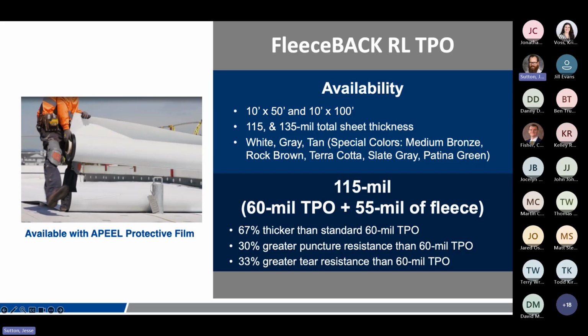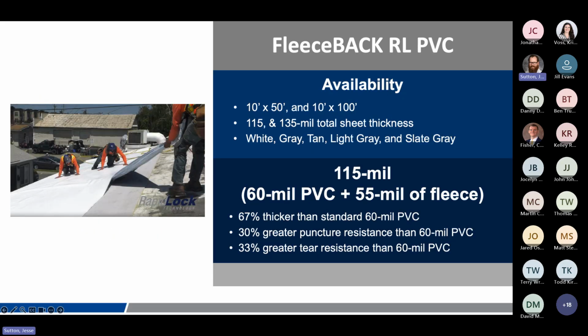Down below there, again, similar performance. We have the increased thickness due to the fleece, 30% greater puncture resistance than a bareback sheet, and 33% greater tear resistance, again, with adding that exterior reinforcement. Just to move on to the PVC offering, again, you can see the roll sizes there on your screen, 115 and 135. A little bit different. We have stocked colors of white, gray, tan, light gray, and slate gray on the PVC side. We don't offer those special colors like we do on the TPO side in PVC. Very similar puncture resistance and tear resistance improvements on the PVC side as well.